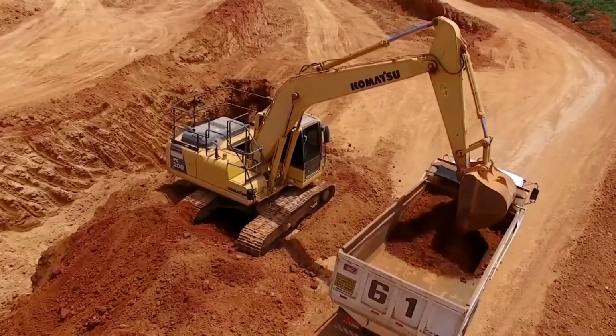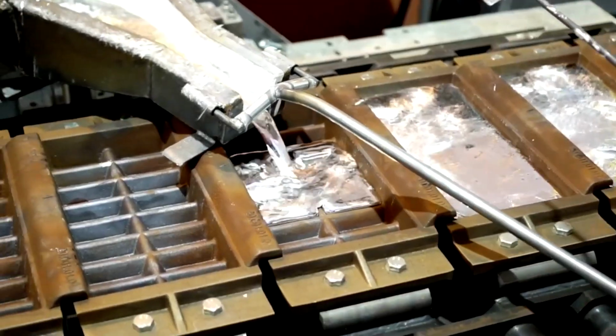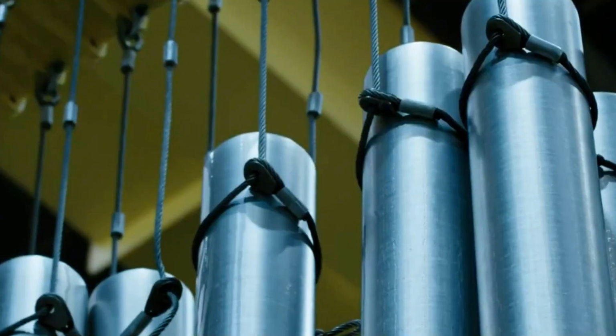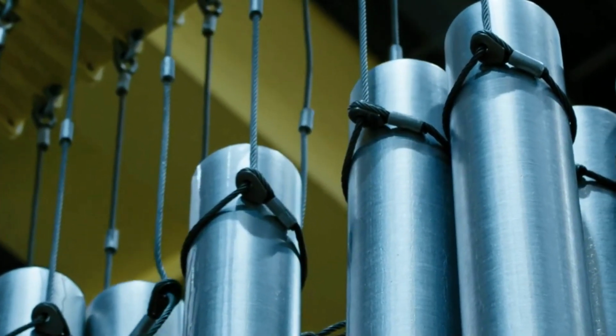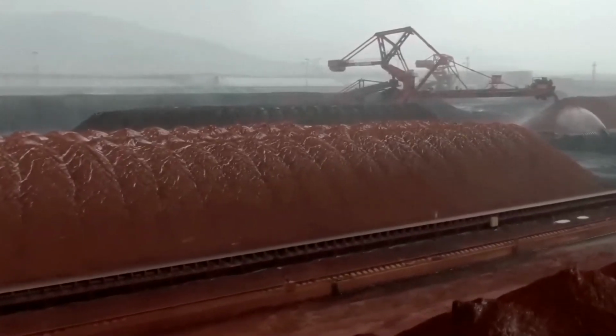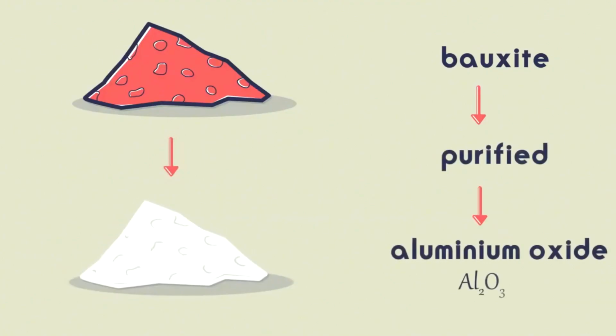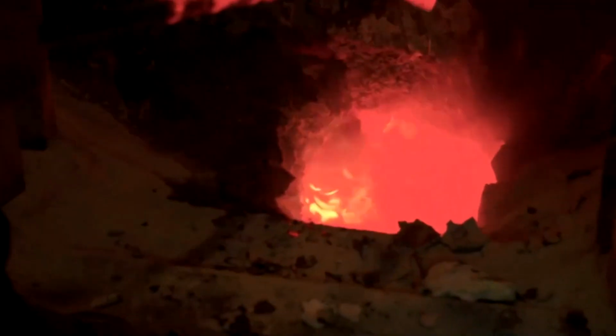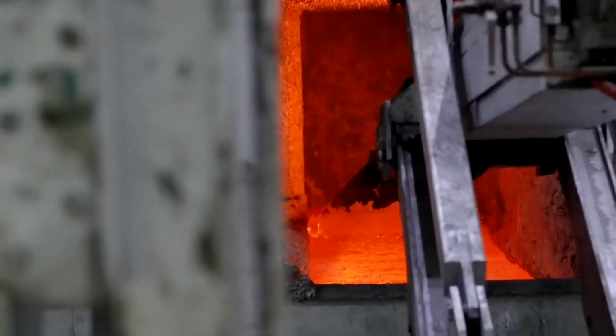At first glance, the white alumina powder looks chemically simple, but in reality, transforming it requires an intense electrolytic reduction process. The purified material is transferred into cells containing a molten electrolyte bath maintained at nearly 1,800 degrees Fahrenheit. A powerful direct current is applied, forcing the aluminum to break free from its chemical bonds.